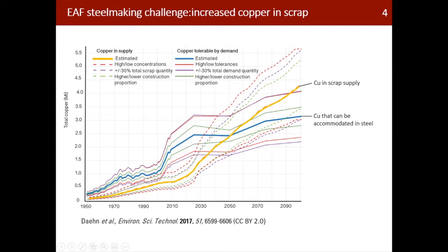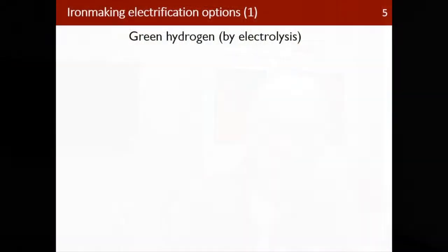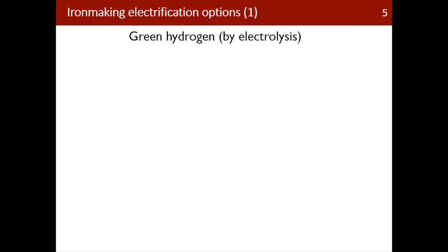Copper has various quality issues, especially surface quality, if there's too much of it in there. So we are definitely heading for a crunch in terms of scrap quality, which is a real danger to our ability to maintain this low carbon recycled steel path. The alternative then is to electrify the iron making step. So where we take iron ore, iron oxide, reduce that, make fresh iron, which then doesn't have any copper in it. And one set of options then starts with green hydrogen.